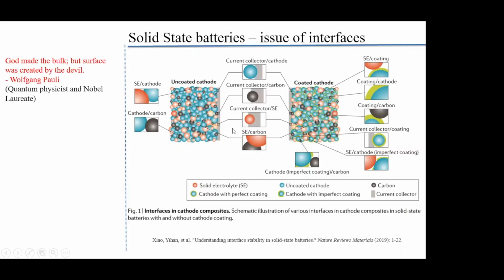So lithium has to have impeccable diffusivity through all these interfaces. You need to improve many of these, and make sure the interface is conducive for lithium transport at a fast rate. So when you press the gas pedal, it is able to give that energy. That means lithium is trying to pass through all kinds of interfaces here. So the more interfaces you have, the harder the problem gets.